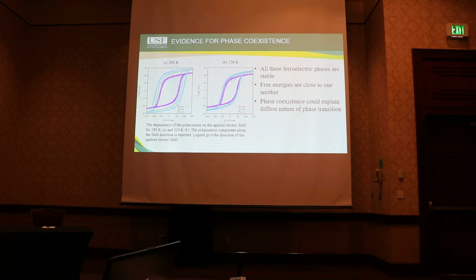So here we have the dependence of the polarization on the applied electric field for 280 Kelvin and 320 Kelvin, where purple corresponds to the 100, green corresponds to the 110, and blue corresponds to the 111. As can be seen, all 3 ferroelectric phases are stable, which is a manifestation of the free energies being very close to each other. Interestingly, this occurs for the entire temperature range for this concentration that we investigated. And such phase coexistence could explain the associated diffuse nature of the phase transition of this material.